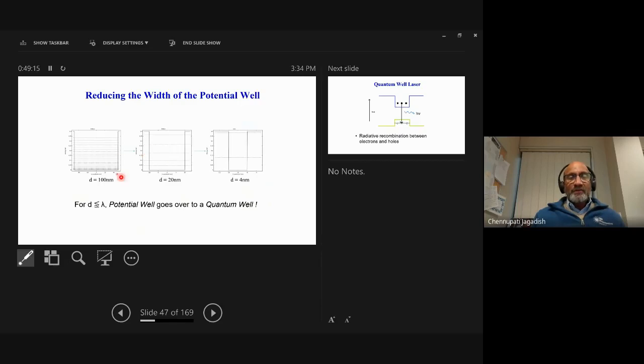So now if you look at the density of states, for example, if the thickness of this gallium arsenide is about 100 nanometers, you get many levels here. But if you reduce the thickness of this gallium arsenide to 20 nanometers, it can support a few energy levels in the density of states. But if you really go to smaller thicknesses of 4 nanometers, you can see only the ground state and the excited state, and that means the electrons are either sitting here or there. So this is the so-called quantum well which I'm talking about.